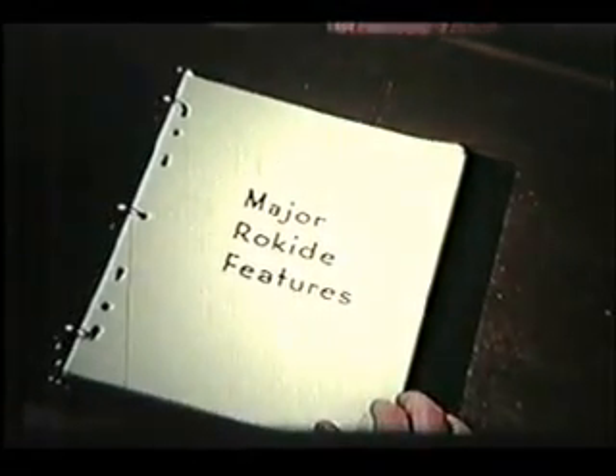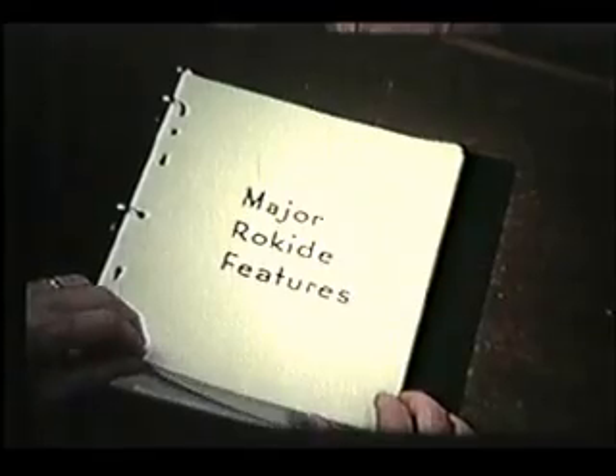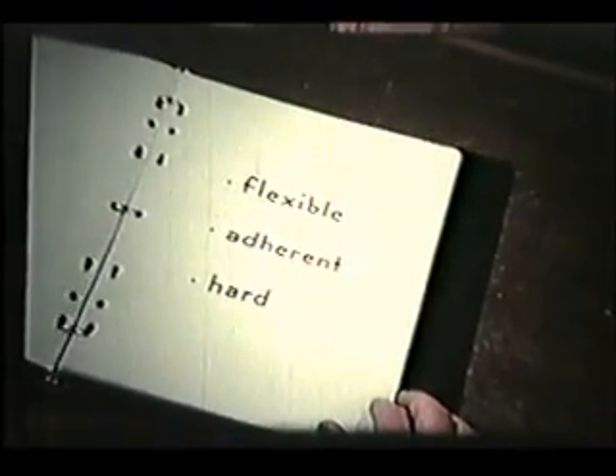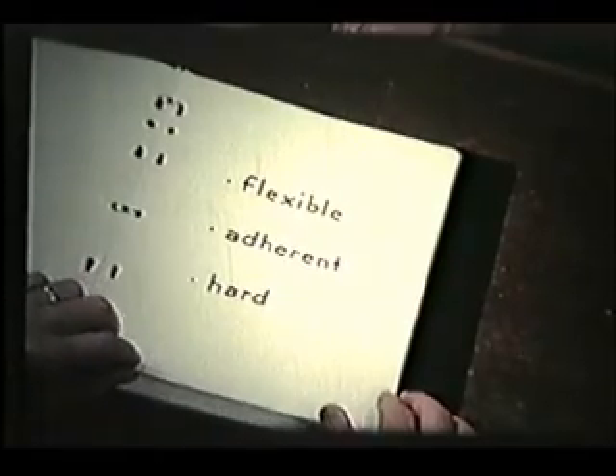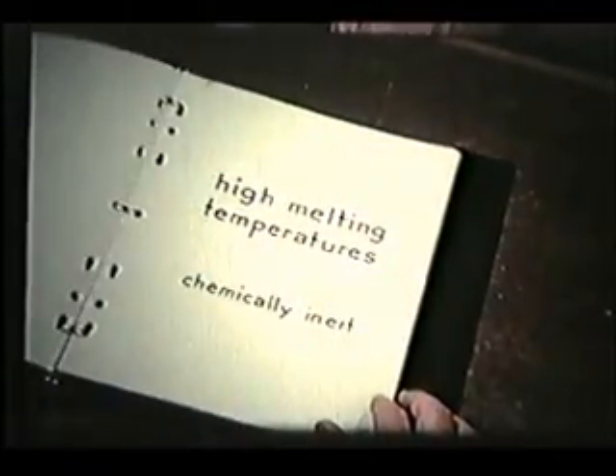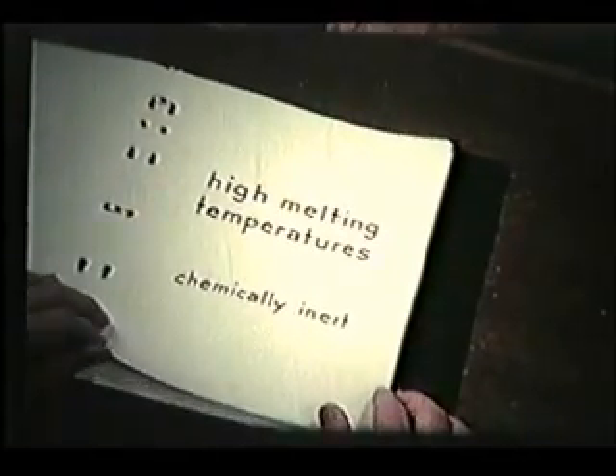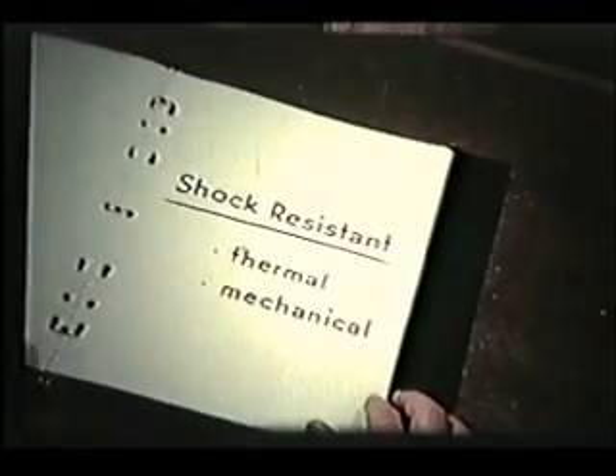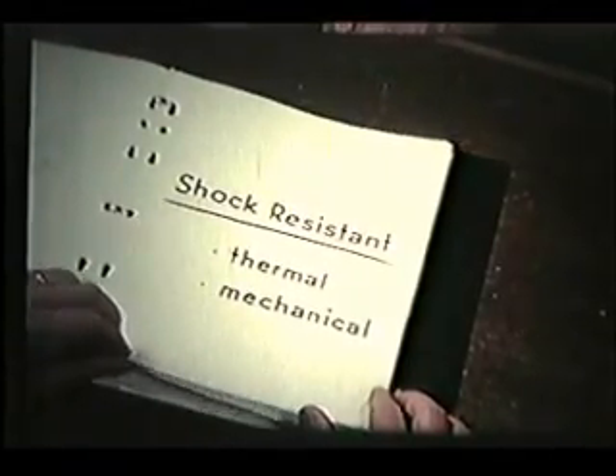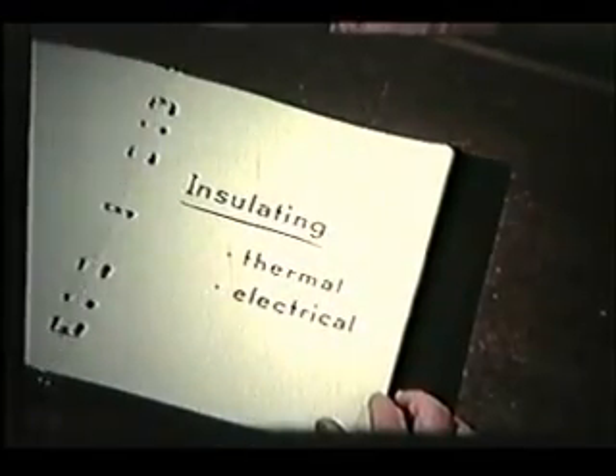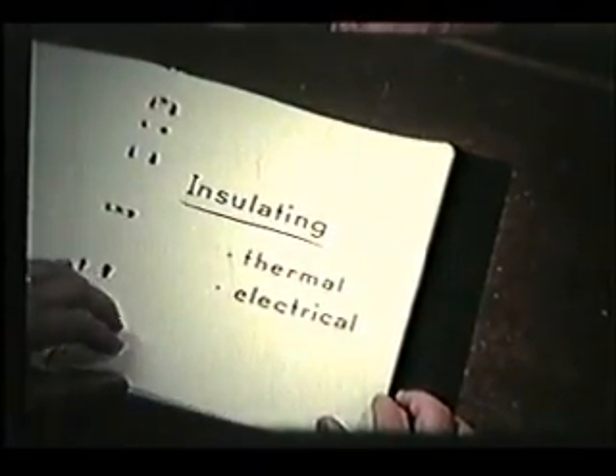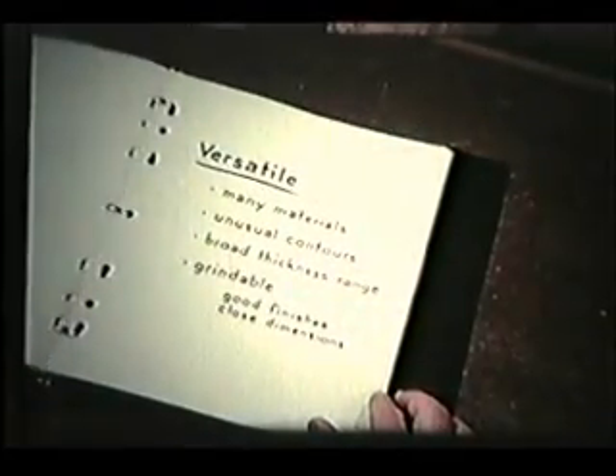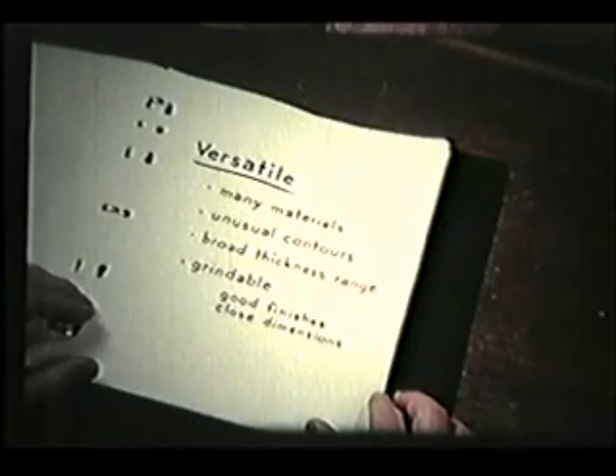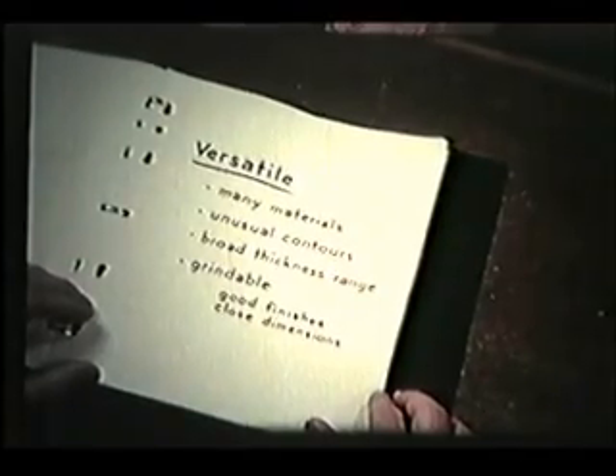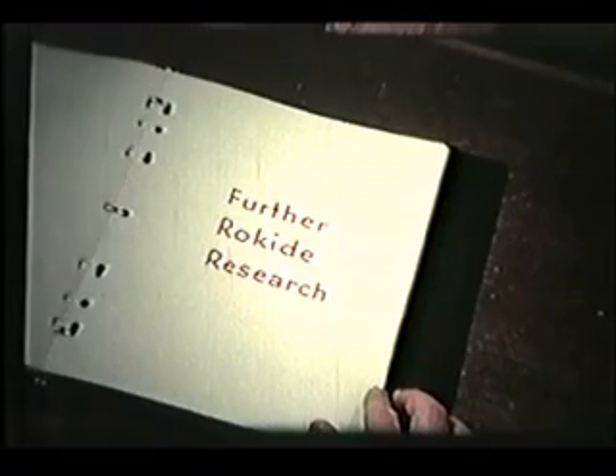Here let us summarize the major features of the Rokide coatings. They are flexible, adherent, and hard. They have very high melting temperatures, up to 4600 F, and they are generally inert to all chemicals. Demonstration and use have shown them to be excellent against thermal shock and capable of withstanding severe vibration and impact. The coatings provide excellent thermal and electrical insulation. They are applicable to many types of materials of unusual shape, and coatings can vary from a few mils to 1/4 and 1/2 inch thicknesses. They can be ground to excellent surface finishes in close dimension.